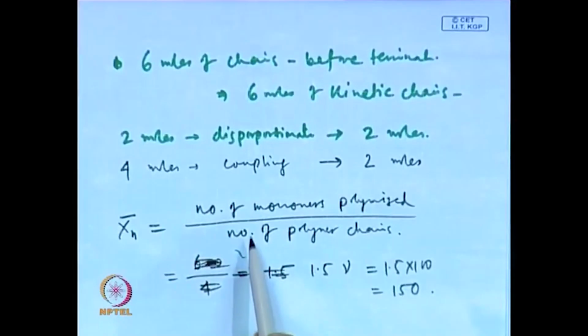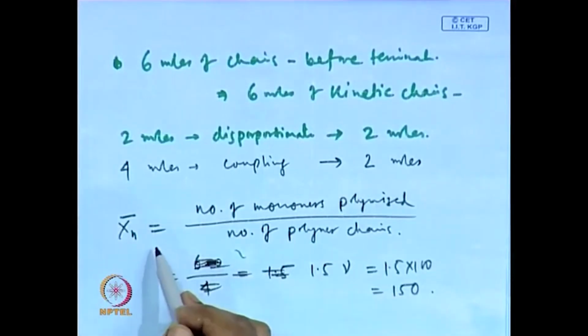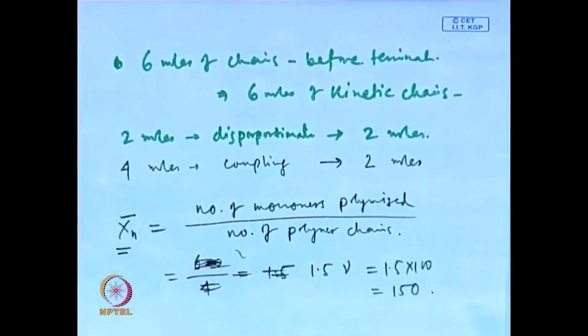Okay. So, that is one fundamental difference between chain polymers and step polymers. How do we understand what the average degree of polymerization, or the average number molecular weight, means? In the chain case, we do not consider the monomers, whereas in the step polymer case, we consider every molecule present at the end of the reaction.